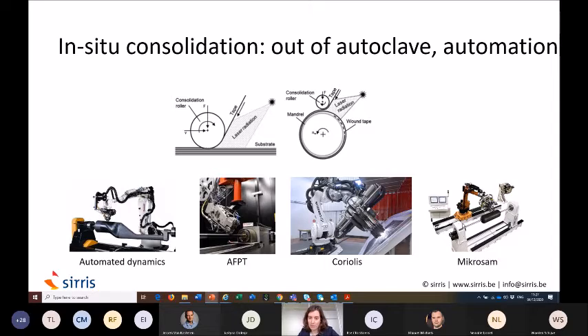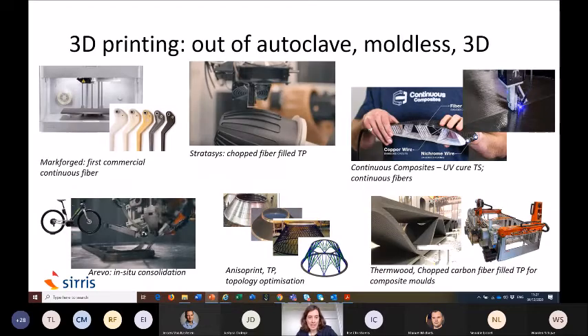Here are some examples from commercial players at the moment to make this kind of tape laying, as we call that. This is fully out of autoclave. You don't need high pressures. It's because it's very local. You need a fairly small force that can be applied by a robot, and you can apply the high temperature through laser radiation, for example. So this is used for tanks, hydrogen tanks, for example, which can withstand a pressure of around 700 bars, can be made in this kind of technology.